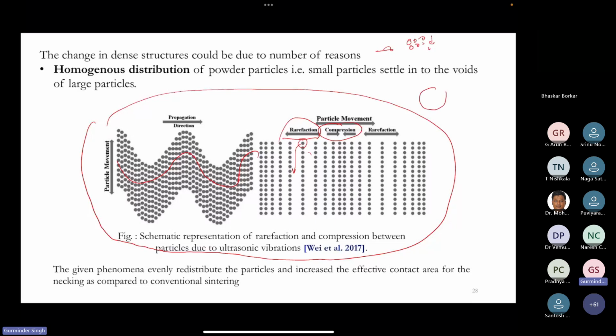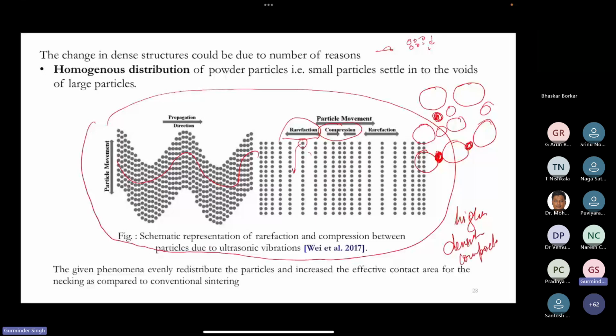So we have chosen a mixture of particle sizes, small particle size and large particle size, it was variable. When we give vibration at this stage, the small powder particles can easily fill the voids of the large particles, and it will give you a higher density of compaction. So powder is highly compacted using vibration at room temperature. Higher density compaction at room temperature gives you effective contact area to make better necking as compared to conventional sintering. That is the first point.